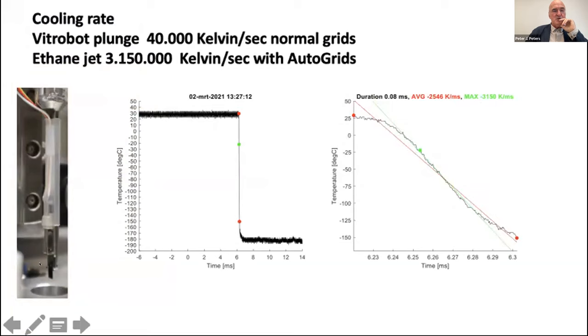It's called Dense Solutions. Material scientists know this because Dense Solutions makes MEMS devices to study catalysis, where you can follow in situ in a microscope, at 200 degrees Celsius, a particular process in time. We discovered that these devices also work very nicely at very low temperature. So you can easily imagine having it not only at 30 degrees, but also 40, 50, or precisely 37 degrees, where cells are happy, or 39 degrees for temperature-sensitive cell mutations.